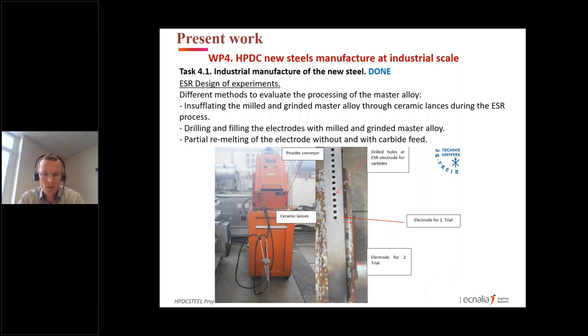Further on, it was very important for us to understand how to add the master alloy at an ESR plant on industrial scale. For this, we developed two ideas. One idea was to drill holes into the electrode. This is an example of a rectangular electrode, which we used for laboratory-based experiments. In these drilled holes, we fed the master alloy. The other method was feeding the master alloy using ceramic lances, by a continuous feeding system into the liquid slag pool during ESR melting, and over this to have a dissolution into the steel matrix.